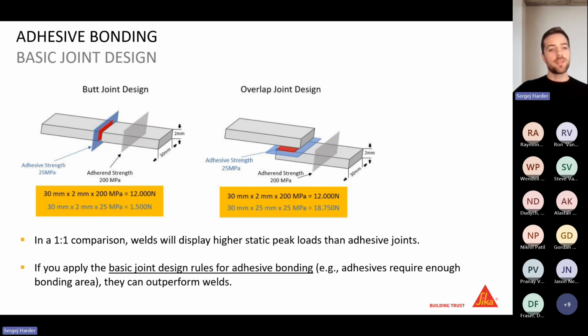So in order to make adhesive joints work, you have to create some surface that you will need for the adhesive to act. And that you can see on the right part, the mainly used design for connecting parts with an adhesive is the so-called overlap joint. In that regard, you still have the same substrates, but in that design, you created the surface, which is now the 25 millimeters overlap. And using the 25 millimeters width that you had previously, you now created a much larger surface for the adhesive to act. And now you can transfer much more load through this design. In that case, roughly estimated 18.75 kilonewtons. And in that design, again, the adherent would be the limiting factor rather than this joint connection.